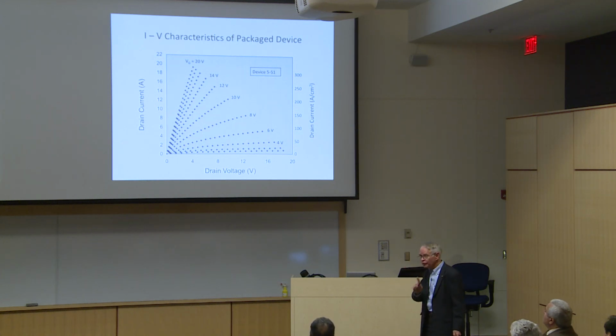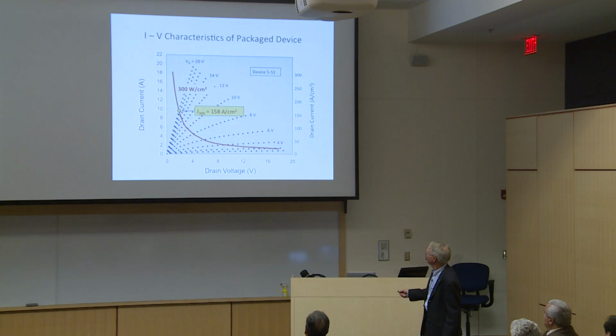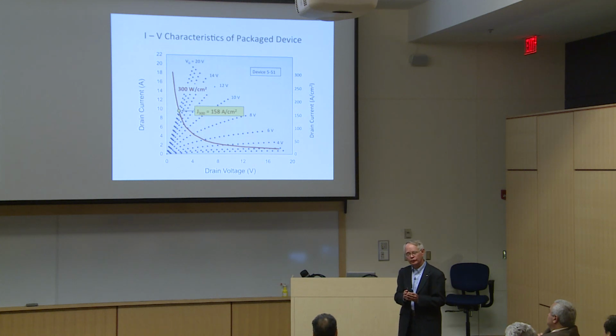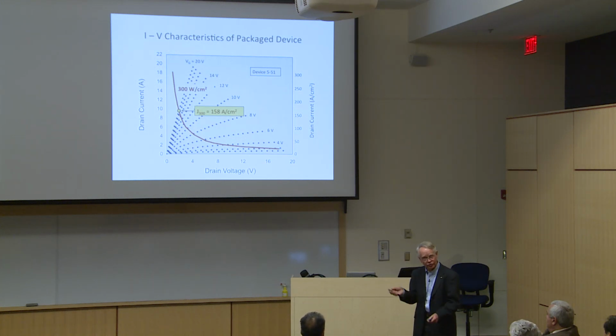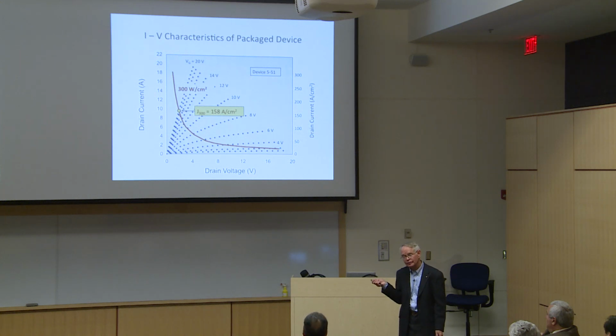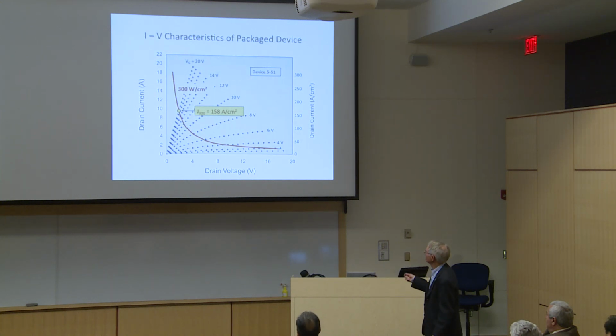And now the real figure of merit, you remember what I showed you earlier, is what is the current at a power dissipation of 300 watts. Here's your line, and that point is actually 158 amps per centimeter squared. This is a smaller device, but if you built 1 centimeter square devices, and people are almost there now in the production devices, this transistor would carry 158 amps. Now, this is some current. So this is pretty good, and we were really happy to see that.